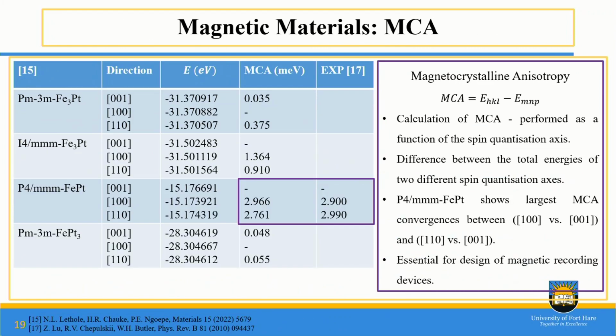We also went on to calculate what we call the magnetocrystalline anisotropy, which is the energy difference between two axis directions of magnetization. So what we basically do is that we tell our system, or our CASTEP, the code that we are using to simulate, that we want you to optimize the structure along the 001 direction, optimize the structure along the 100 direction, and also the 110 direction. We have also done other directions, but we could not find any significant difference.